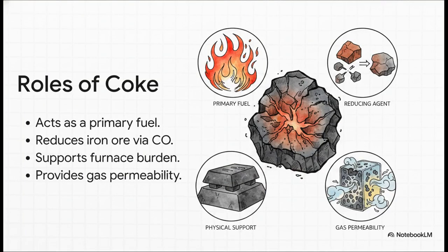We can't just dig up raw coal and chuck it straight into the furnace. It just doesn't work. It lacks the physical strength and chemical purity. An operations engineer knows that coke is actually a multitasking powerhouse. Sure, it acts as a primary fuel, but it also serves as a crucial reducing agent, meaning it strips oxygen away from the iron ore to leave behind pure metallic iron. On top of that, it literally has to physically support thousands of tons of raw materials piled high above it inside the furnace, all while providing the essential permeability that lets hot gases flow upward. It's a pretty tall order.